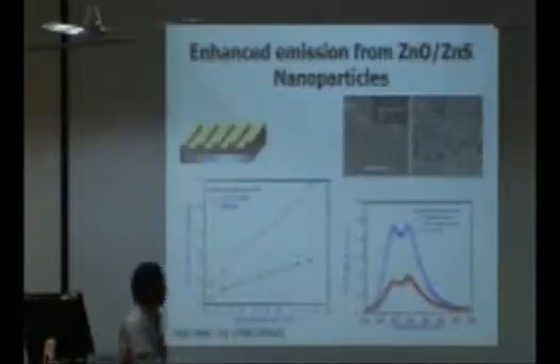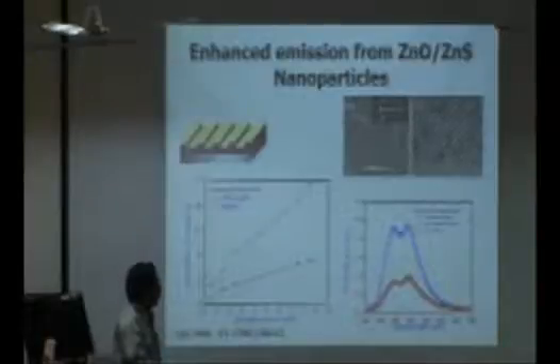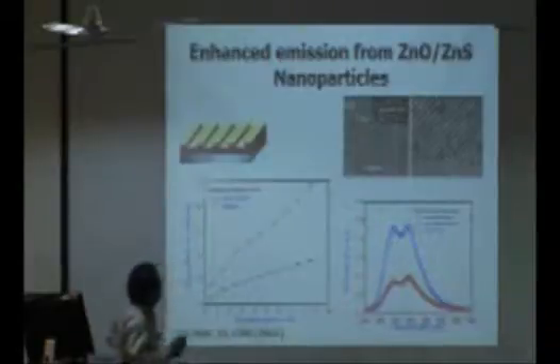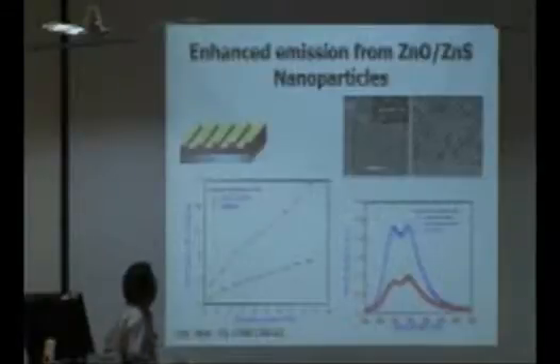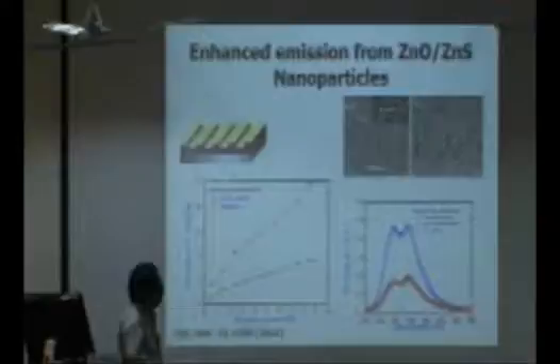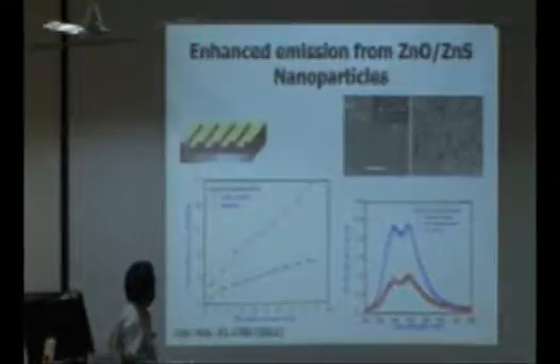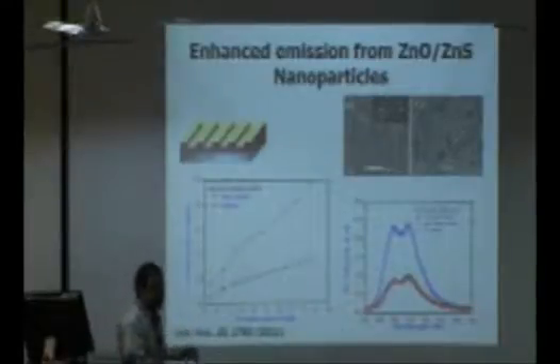We also looked at this from the light source point of view, green or visible light sources. We looked at zinc oxide, zinc sulfide core-shell nanostructures, which when we place on top of these nanopatterned structures, we showed an enhancement of almost 2.5 times in the broadband emission. It also showed a linear behavior, unlike the dots which showed a saturation behavior when they are placed on top of unpatterned quartz.